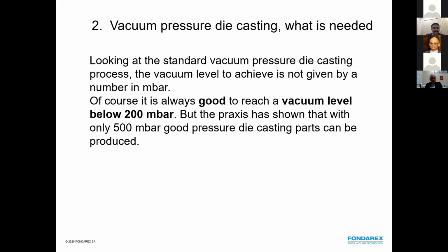And the question is always, how much should we get? People talk about 100 millibar, about 50 millibar, and so on. Me, I have made many good castings at 400 millibar. Why? Because we didn't have the time to get good vacuum, or sometimes also, as we will learn later, if the vacuum is getting too good, the side effects of the vacuum are getting higher, and not everybody is able to manage them.